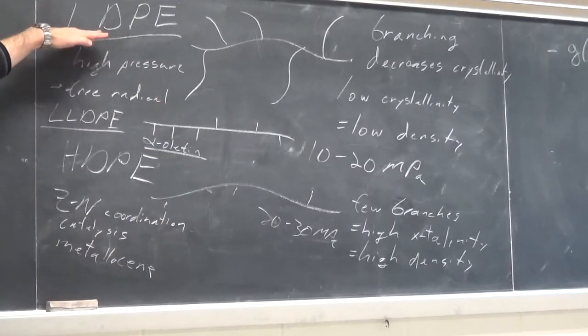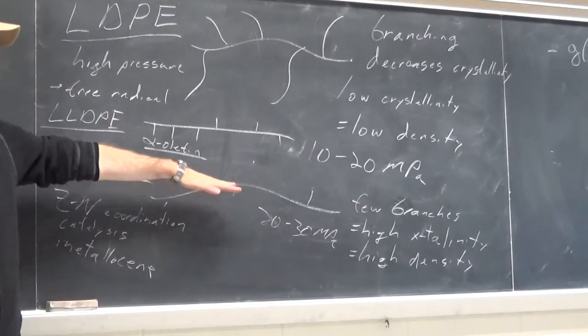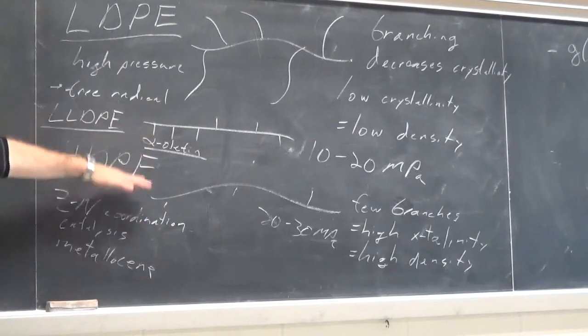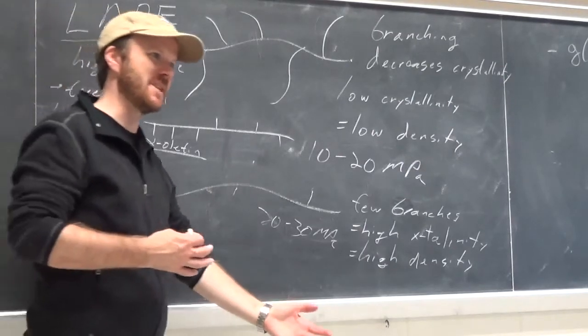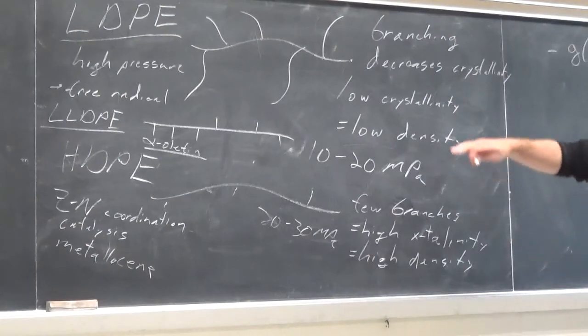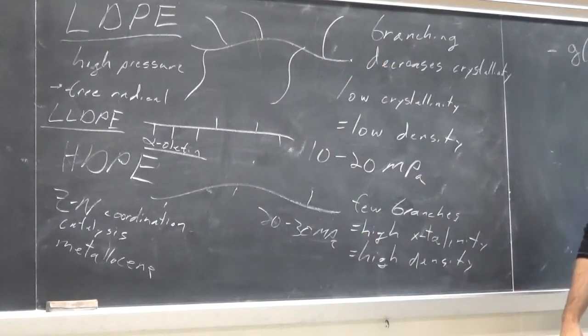But you can't make low density polyethylene with metallocene catalyst because you can't get the branches. And so because the branching is either non-existent or very controlled, you can use metallocene catalyst for these two polymers. Depends on the patent, depends on what technology your company owns. But the only way you can get the branches is by free radical polymerization.